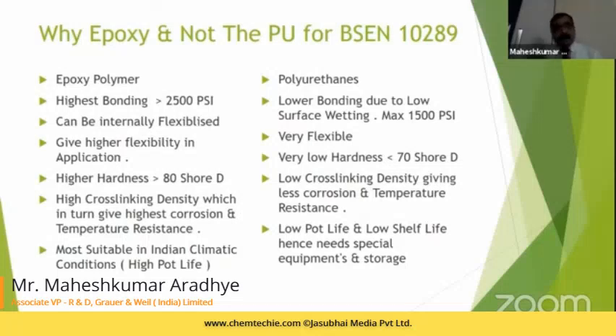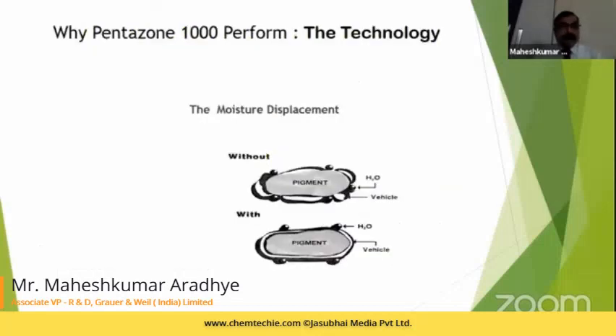As far as polyurethane is concerned, as you go on increasing its hardness, its pot life gets shorter and shorter. It could be something like 60 to 90 seconds when it gives you a hardness of say 70 for sure. But when you decrease the pot life, it decreases the surface wetting, and that's the reason you will get lower adhesion to the substrate. That's why I always say that a material like BS EN 10289, or most pipeline external materials, should be made of epoxies and not polyurethanes. That is the one constraint.